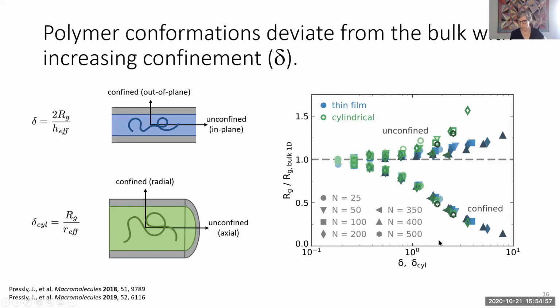And the first thing we notice, and this is probably not surprising if you've thought about polymers up against rigid walls, is that there's a change in the polymer conformation. So here we're comparing the confinement of the thin film and the cylinder, both as a function of this confinement parameter. And we've divided the change in the radius of gyration conformation into two parts. So you have this polymer and you have a radius of gyration. You can break that into a component that is perpendicular to the confinement direction and parallel to the confinement direction. So you have a confined and an unconfined radius of gyration.